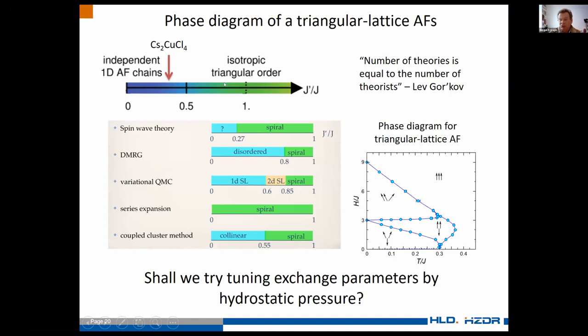So from spin liquid to this isotropic triangular order, because when J prime over J is zero, these are independent one-dimensional antiferromagnetic chains, so the ground state is already a spin liquid. If you look at the literature, you will see a lot of different theories, and they are quite different, I would say. The idea would be to tune the parameter J prime over J using hydrostatic pressure.